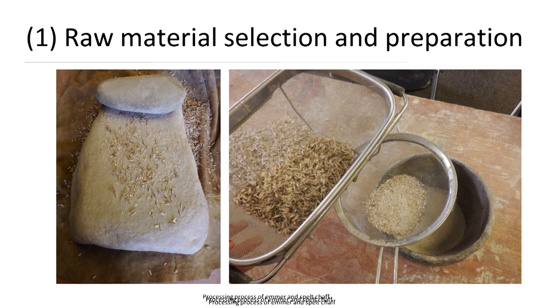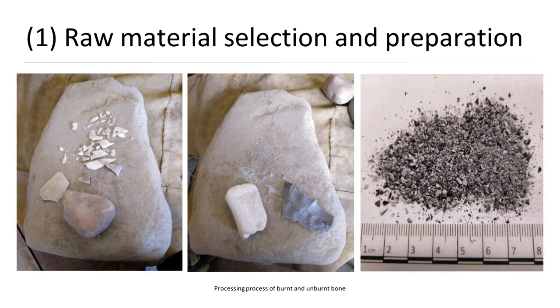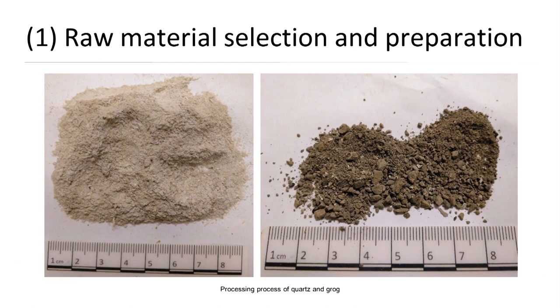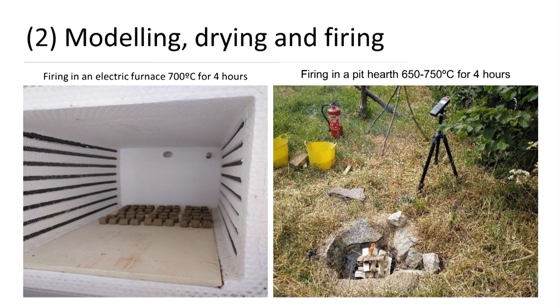The first stage of the methodology was to prepare the raw material. Clay was collected from the Wicklow Mountains in Dublin, and tempering materials were processed until obtaining a 2 mm size. We selected plant chaff, emmer and spelt, burnt and unburnt bone, also dung, and then quartz and grog. The second step was modeling the specimens into two different shapes, cube shape and bar shape. These shapes were selected specifically for the technological tests. All of them contained the same amount of temper, 10%.